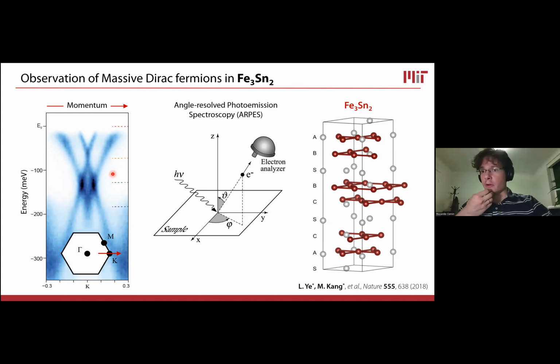This actually came out from the very first experiment we did on these samples. This was led 100% by Mingu, where we looked at the dispersion of the electronic bands across the K point. And so if this system was similar or equivalent to graphene in the vicinity of the K point, what you would expect is a pair of Dirac fermions meeting at a Dirac point, right at the K point. So in other words, you would expect a single Dirac cone. And you do see a Dirac cone, which has a binding energy of about 60 milli-electron volts up here. But then there is a second Dirac cone. So there is a second pair of Dirac bands that has a Dirac point at a deeper, larger binding energy.